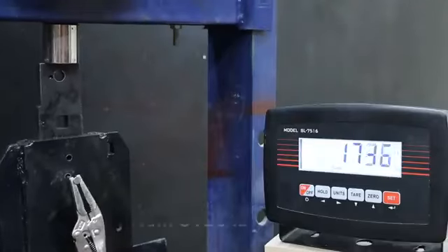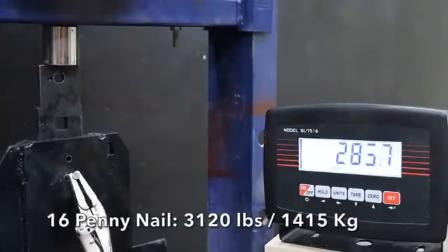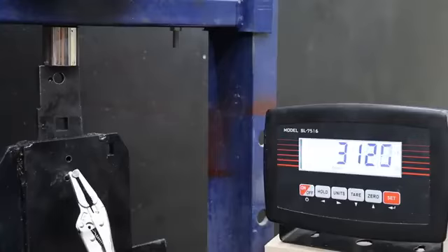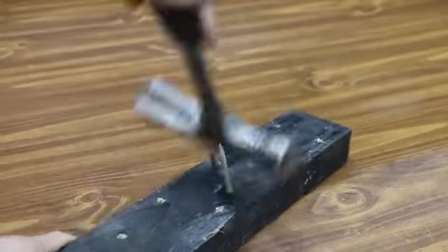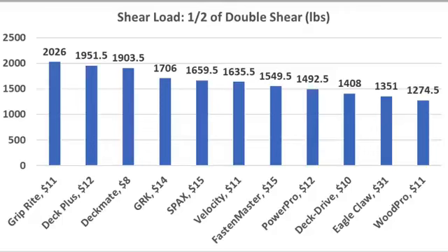And the 16-penny nail did better than some of the screws at 3,120 pounds. I definitely don't recommend using screws for structural projects unless they're building code approved, since screws are more brittle and can break off from repeated back and forth movements. So the Grip Rite came out on top at 2,026 pounds. Deck Plus performed very well at 1,952, Deckmate 1,904, GRK 1,706, and SPAX 1,660 pounds.